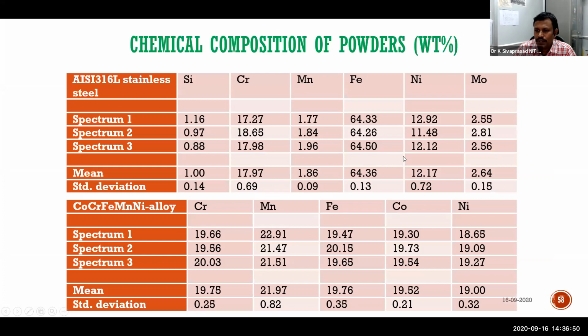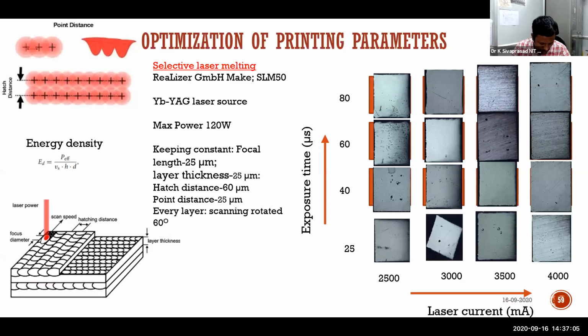Then again chemical composition. Using SEM EDS itself we have done, and we could see that the chemistry is almost matching whenever we are doing it in a number of locations and number of particles. So it is very clear that our chemistry associated with particles is also very good.